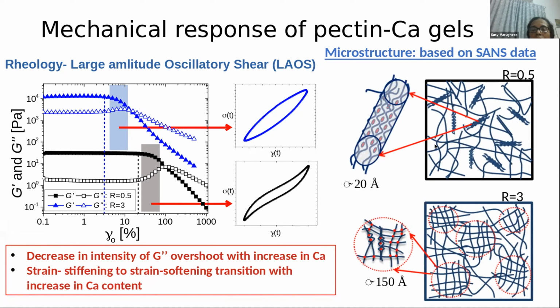So we looked at the microstructure, to see what could be contributing to this behavior, using small angle neutron scattering, and obtained some inputs to understand what could be going on with this material. They do have different kinds of microstructure at low and high calcium, as you can see here. At low calcium, the calcium forms what are known as egg box bundles. These egg box bundles can be very stiff, and the polymer in this situation can behave like a semi-flexible chain network. Semi-flexible polymer chain networks can accommodate some amount of deformation by transferring the load to these rod-like structures. The egg boxes are very rigid, and they can accommodate this kind of strain.